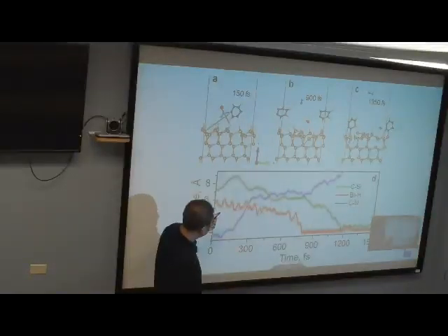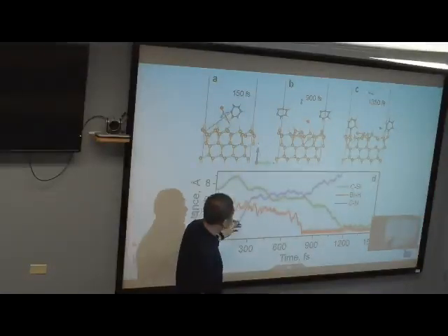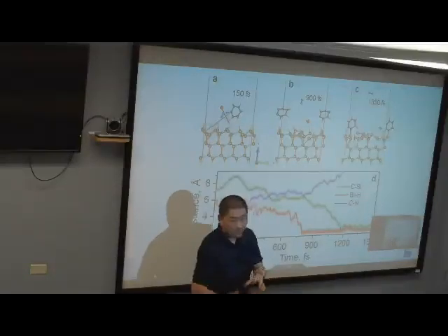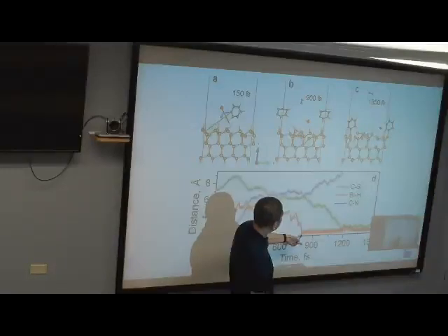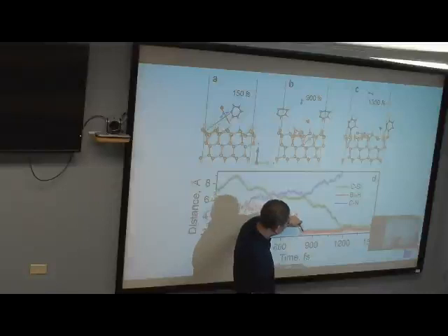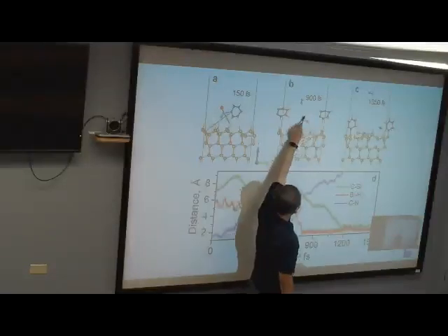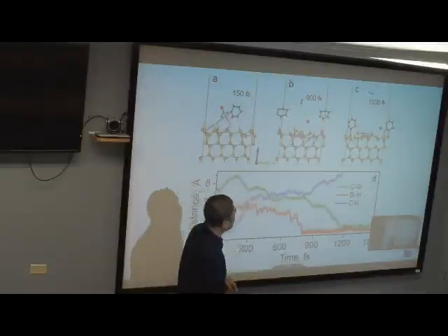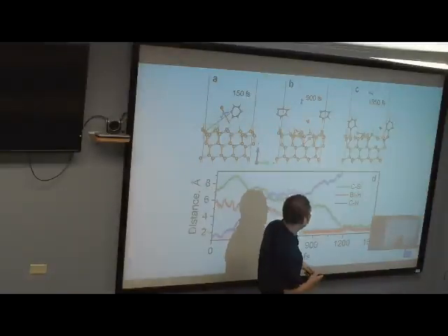The red means the distance between bromine and hydrogen. As time goes by, the bromine approaches the hydrogen, and we can see the formation of the hydrogen-bromine bond. This bond is quite stable; at the later stages, we can see the fluctuation of this bond. This is a hydrogen bromide molecule. And finally, the phenyl group just stays on the surface of the silicon.